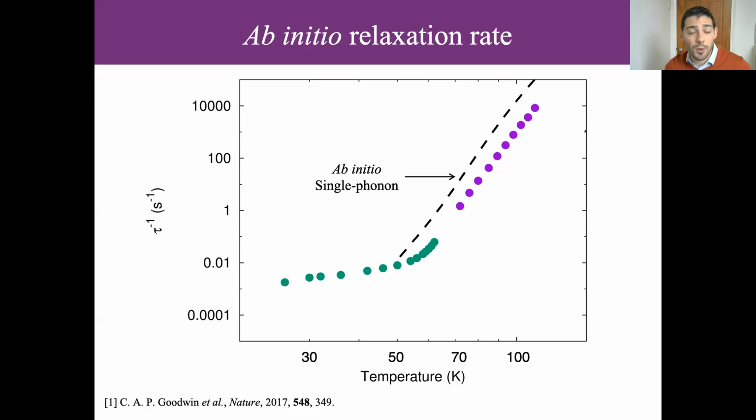The only truly single molecule stuff has really come from Wolfgang Wernsdorfer, who's been doing terbium bisphthalocyanine for many years, which is this double-decker type molecule. That's an okay single molecule magnet, let's say. He's done a lot of measurements of that in gold break junctions, on carbon nanotubes, and I think a few other ones. But for all intents and purposes, he's not measuring relaxation rates. He's not using this as a single molecule magnet. Relaxation rate's an ensemble property by definition, so on a single molecule, it plainly doesn't exist.